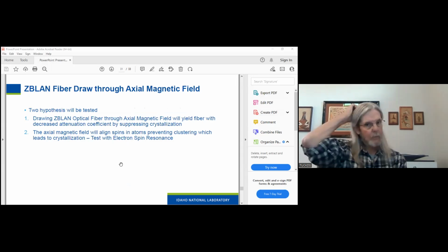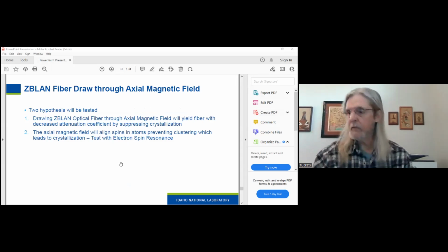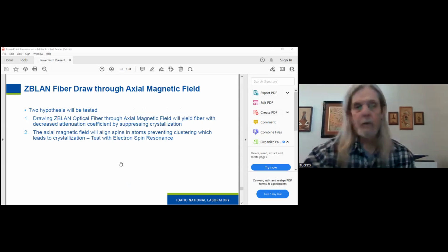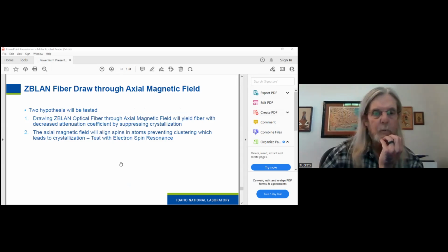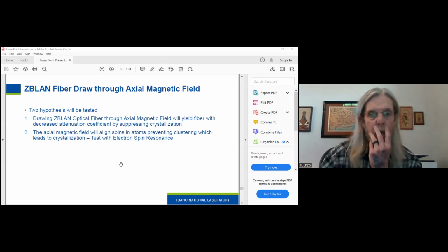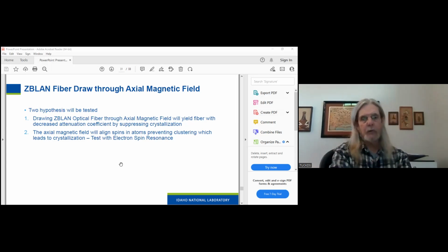So, for drawing through an axial magnetic field, two hypotheses would be tested. One is that it will yield fiber with a decreased attenuation coefficient by suppressing crystallization. The other is that the axial magnetic field will align spins in the atoms, preventing clustering, which leads to crystallization. And I would test that with electron spin resonance.